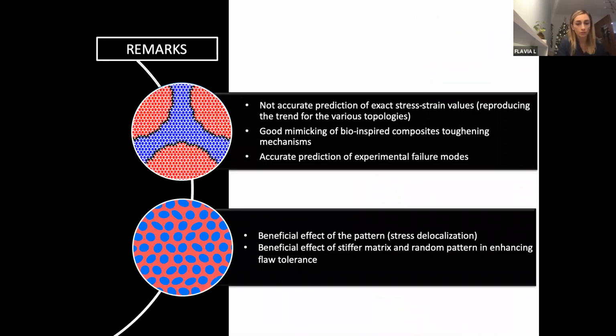So coming to a conclusion, trying to be on time, what we noticed is that with this kind of lattice spring model, they do not really provide an accurate prediction of the exact stress-strain values, although it was not our target, as I said before. But they are able to reproduce accurately the trend of various topologies, and they are a powerful method in terms of mimicking the bio-inspired composite toughening mechanism, and they also provide accurate prediction of the experimentally observed failure mode. Also, we observed a beneficial effect of the pattern in terms of stress delocalization, and a beneficial effect of a stiffer matrix and random patterns in enhancing flaw tolerance.